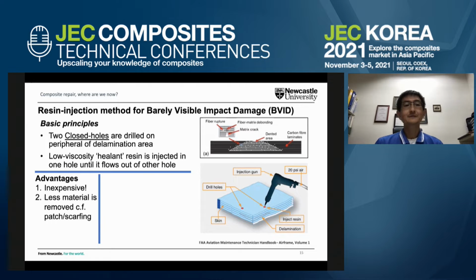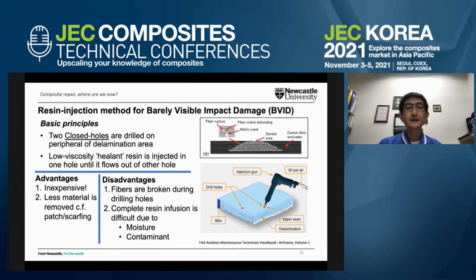Now, the advantage is it's inexpensive. There's very little material removed compared to the conventional method. The disadvantage is because we are talking about drilling holes, good fibers could be broken, and also the resin injected may not completely infuse into the crack.